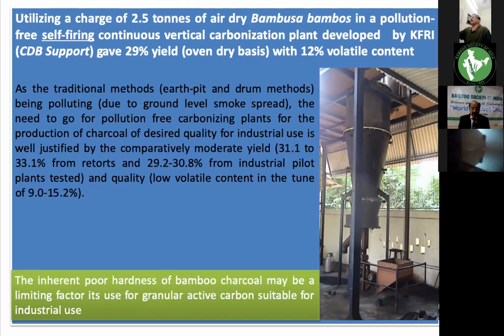As the traditional methods are polluting, the need to go for pollution-free carbonizing plants for the production of charcoal of desired quality for industrial use is well justified by the comparatively moderate yield, 31.1 to 33.1% from retorts and 29.2 to 30.8% from the industrial pilot plant tested, and the quality, with low volatile content in the tune of 9 to 15%. So the charcoal obtained from these pilot continuous plants is also equally good for industrial use.